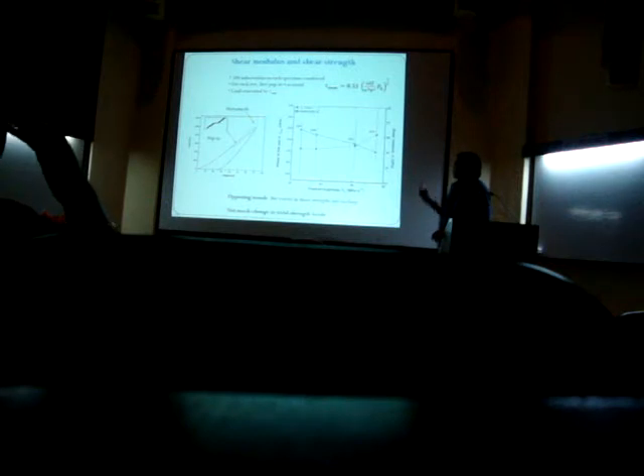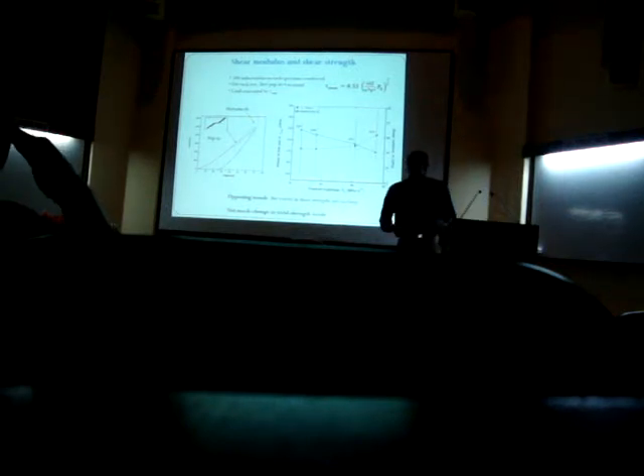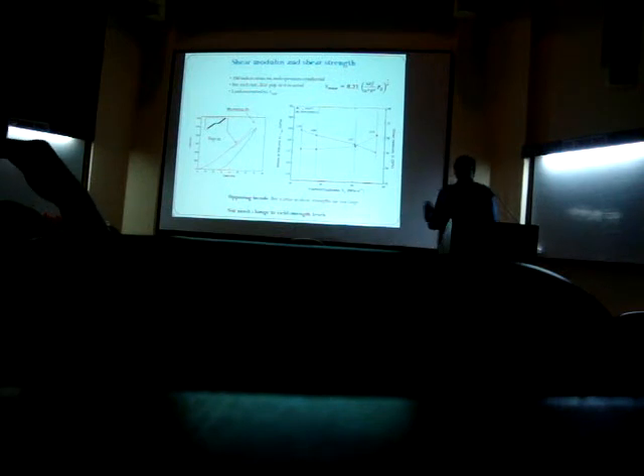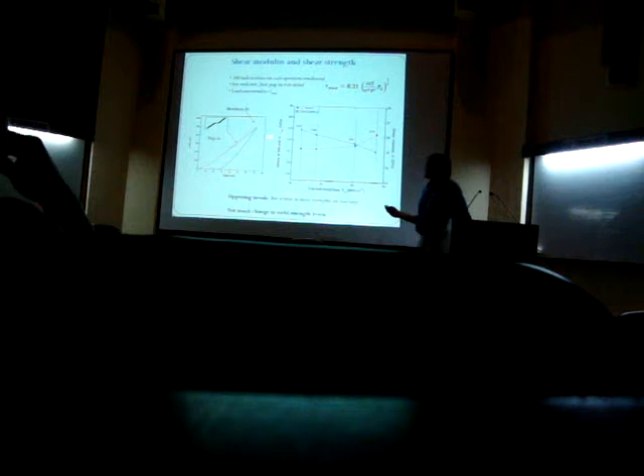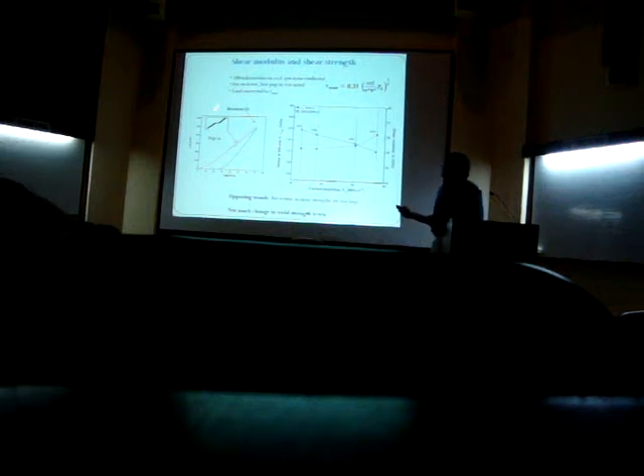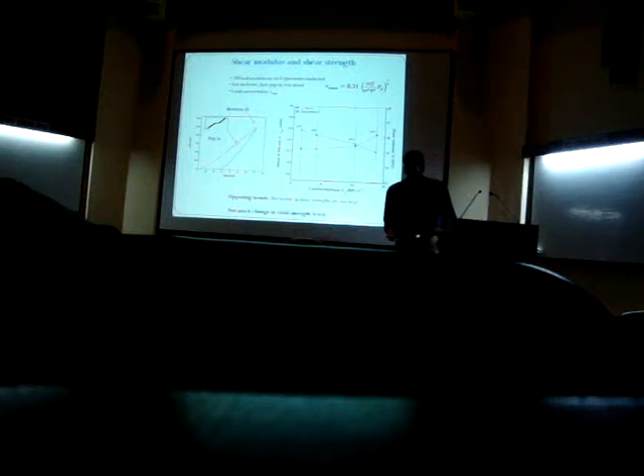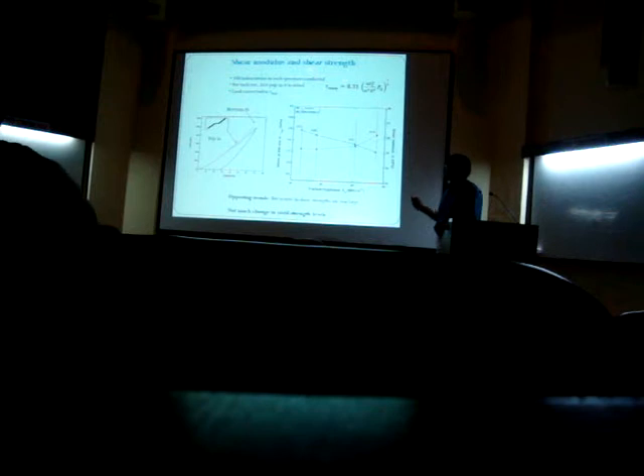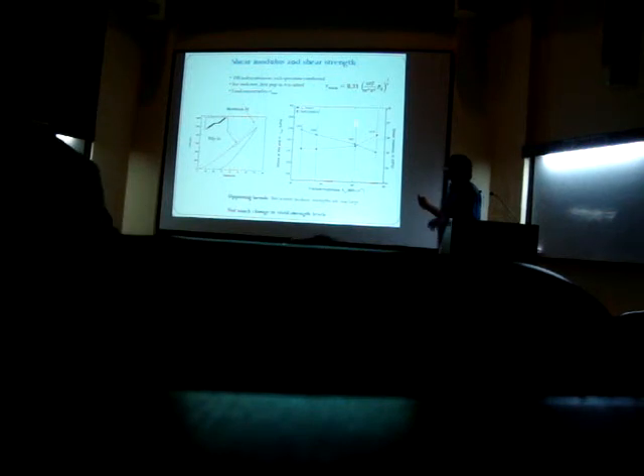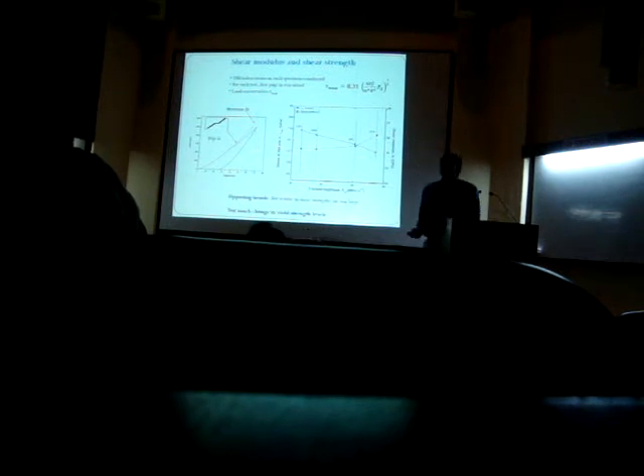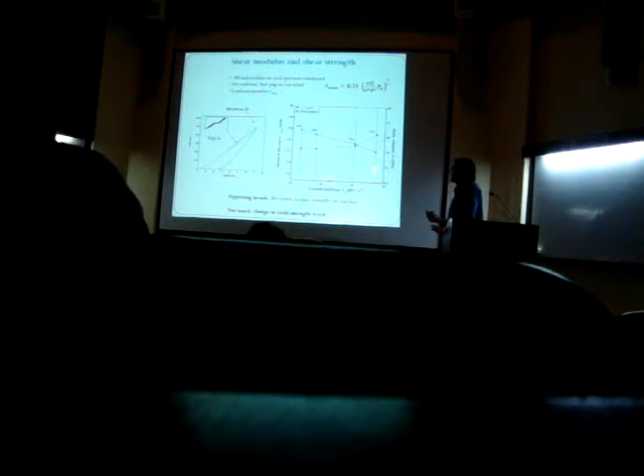So the free volume is now, we keep that in perspective. Let's move on to what other parameter can be evaluated from these glasses. So using nano indentations, that is 100 tests, we were able to measure local yield stress, that is using this equation, or rather the local shear stress, the local yield stress, and we found that initially we thought that it is actually decreasing with, as in the material which has got a higher fracture toughness has got a lower yield stress, but that is not exactly true.